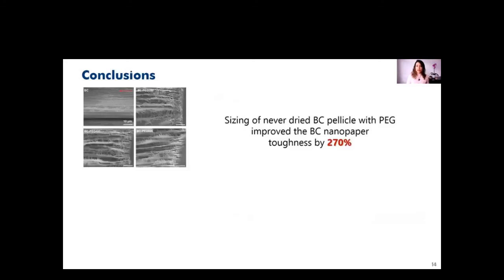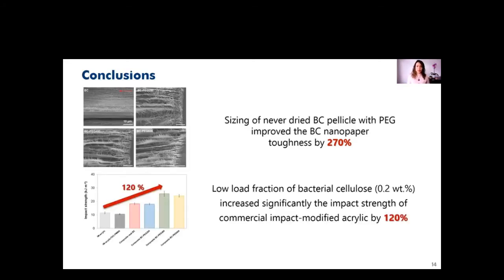nanopapers. As a conclusion, we can say first that the sizing of never dried BC pellicle with PEG improves the BC nanopaper toughness by 270%. And a second conclusion, we said that the low load fraction of bacterial cellulose, 0.2% in weight, significantly increased the impact strength of commercial impact modified acrylic by 120%.